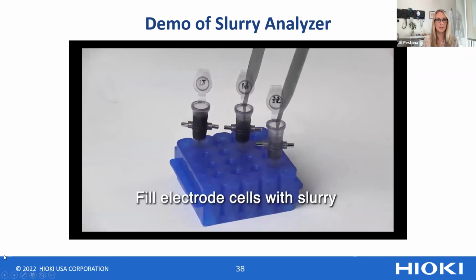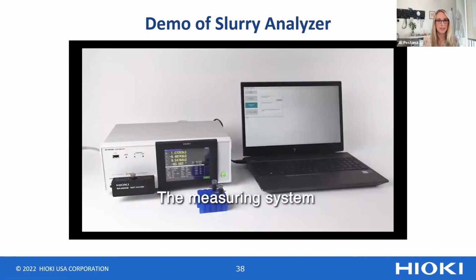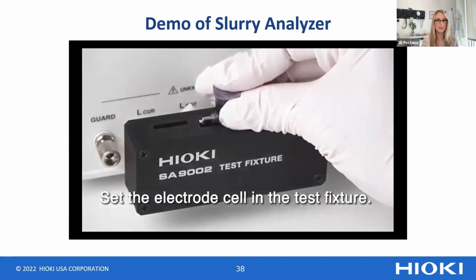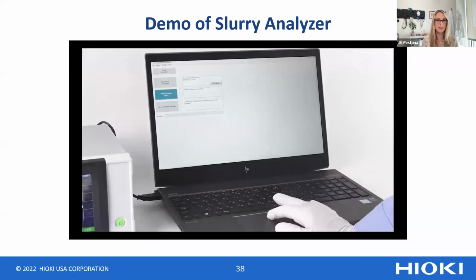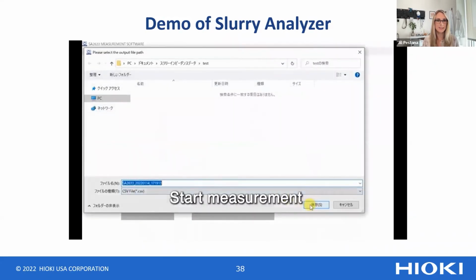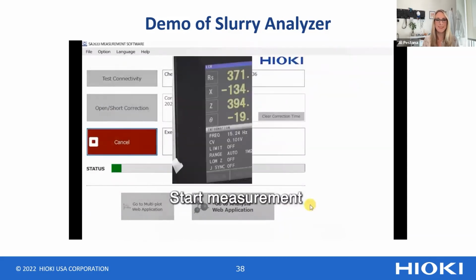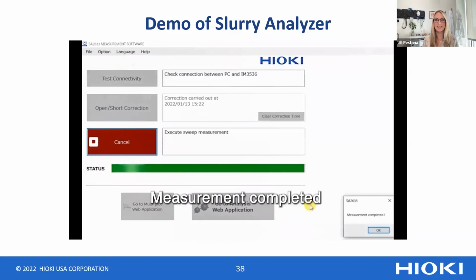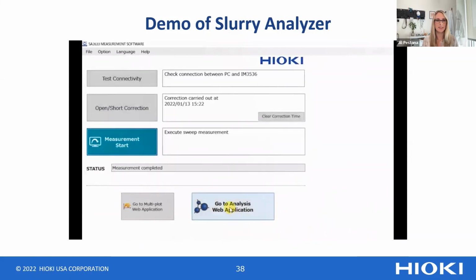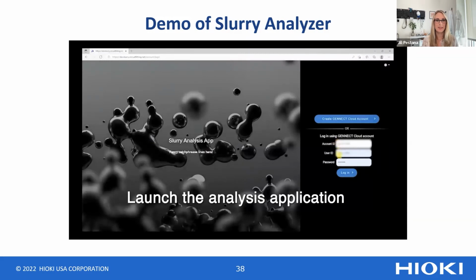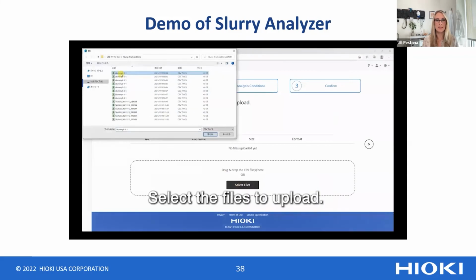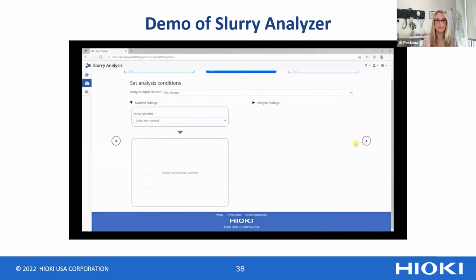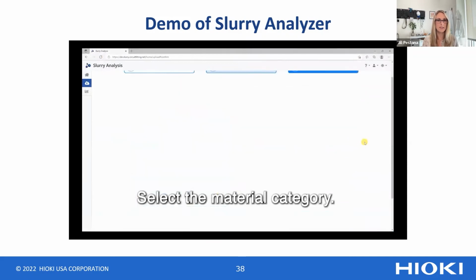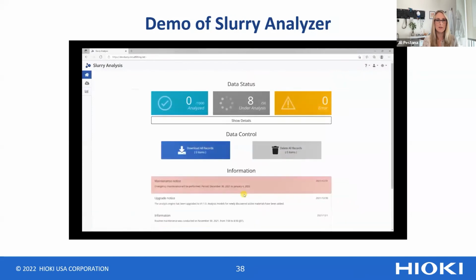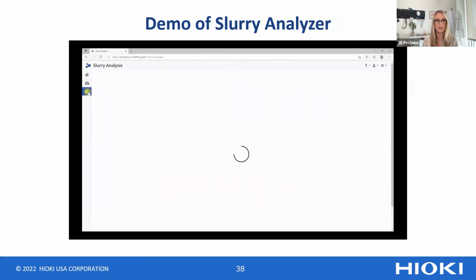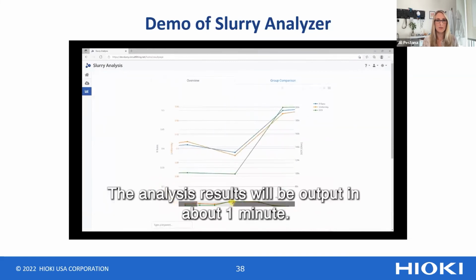So here we have the slurry being filled into the sample holders. And the test fixtures on the cell, you insert that sample into the instrument and start the measurement. Save the file, always an important step, and start the measurement. You can see it displays in real time what those values are. And then it has built-in software to help you do the analysis through the system. You can select the active material, you can select the additives you're using, and submit and analyze those. So it has these presets for all of these materials. And you get your results.